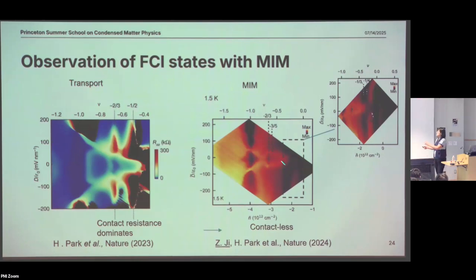So we can do a very similar thing as DC transport. We turn on a magnetic field, we calculate dn/dB, and that slope tells us which state it is. And we indeed tried that. I'm not showing the data here, but it does follow that trend, because it is just a local measurement of conductivity, and that is sufficient. Yeah. I suppose this was a dual gate device. Yes.